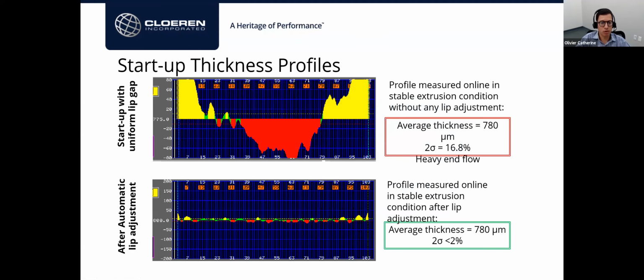However, in real life, when we started this die, we observed this phenomenon. We observed it without doing any lip adjustment. So we gapped the die at the uniform die gap. And you can see that the resulting gauge measurement online was crazy. I mean, we have very heavy end flow and very poor center flow. So the material is all flowing at the edges, basically. This is characterized with a gauging system with flow variation of 2 sigma, heavy end flow of about 17%.